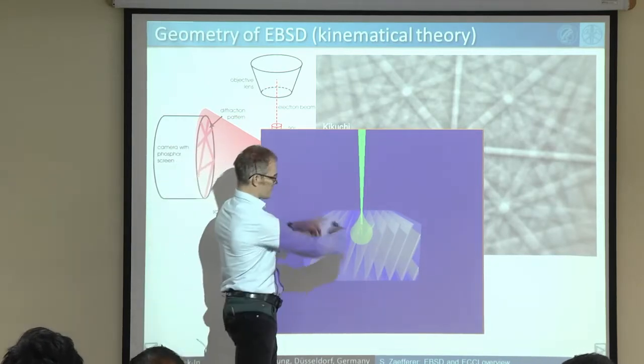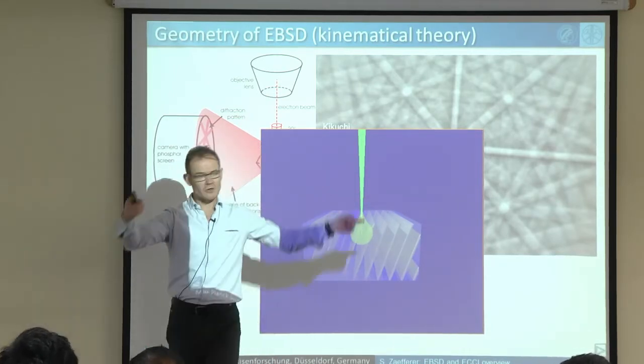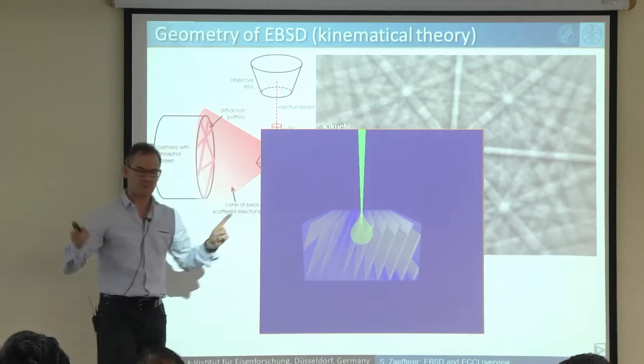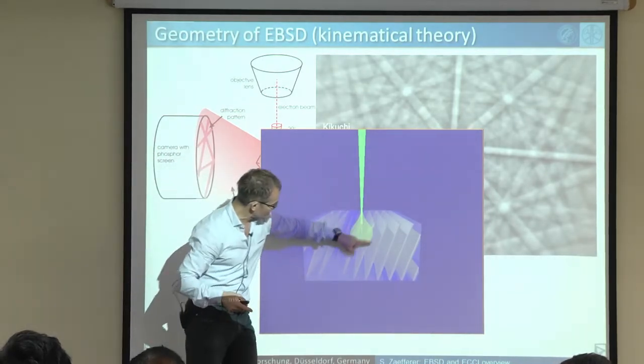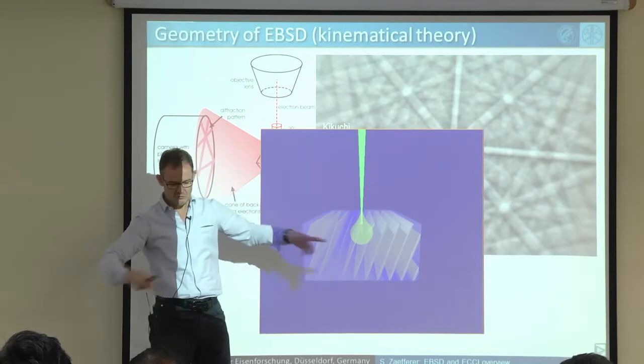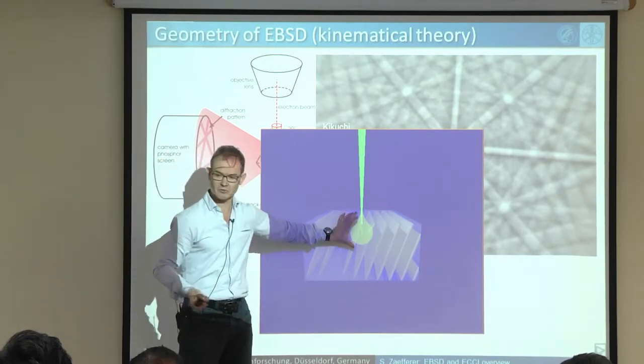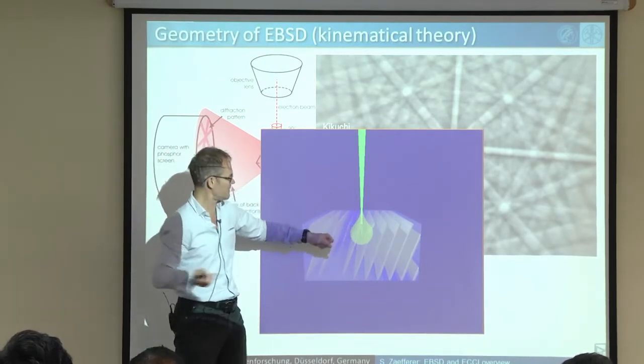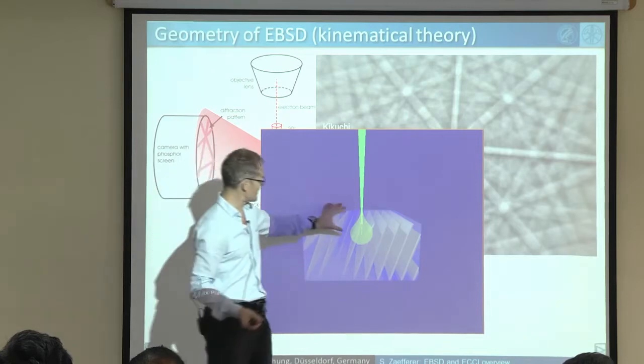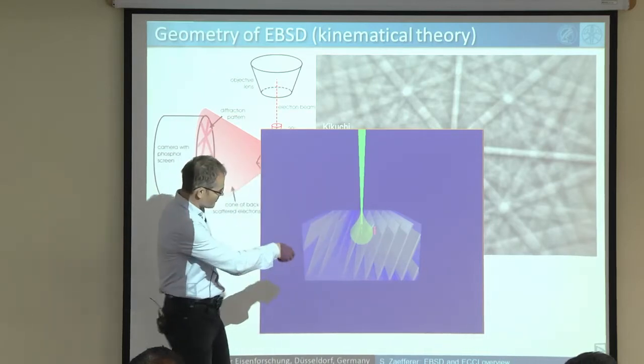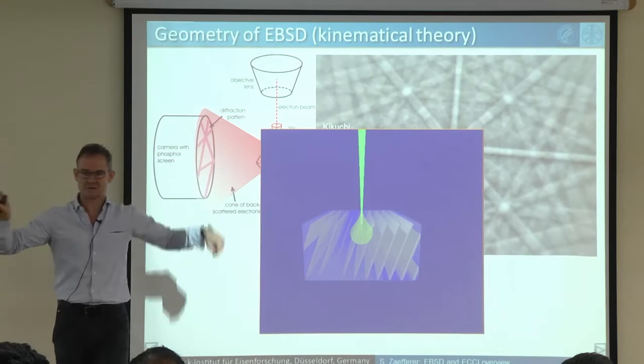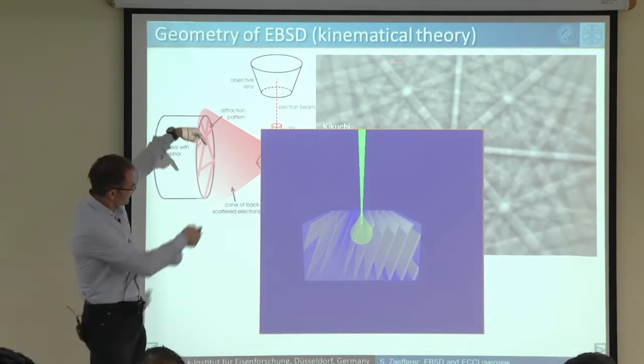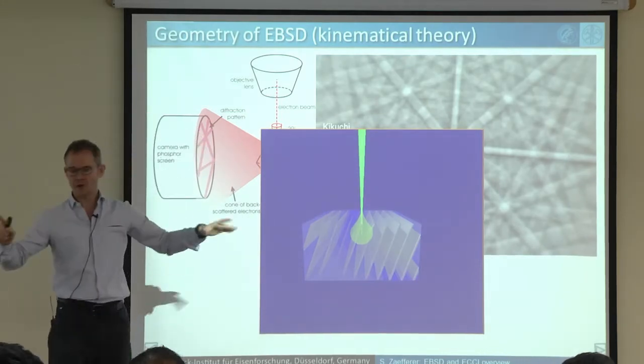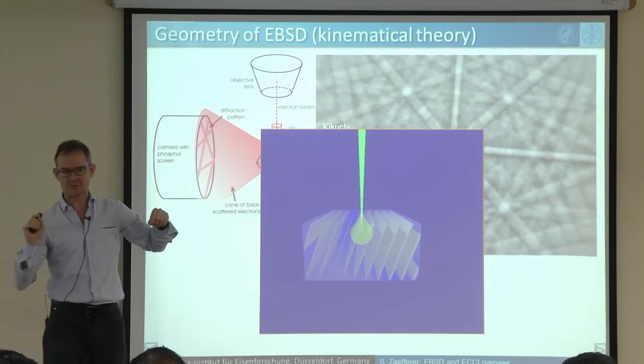You want the electron beam first to be scattered incoherently in all possible directions of space. So we will create a little scattering volume, which is a few 100 nanometer large maybe, or sometimes only a few 10 nanometer large. And in this volume, electrons travel in all directions. So they are no longer following the primary beam direction. They have lost any coherence with the primary beam.